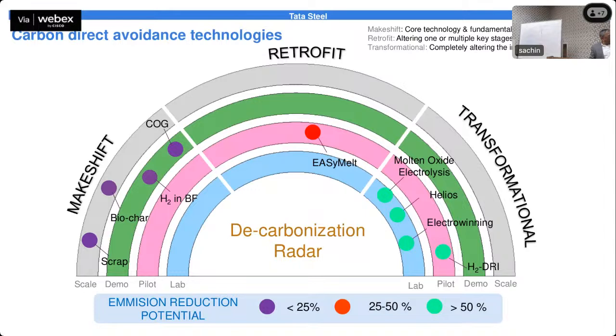But it also means, if you look at the color coding, that the emission reduction potential is only less than 25%. You cannot take care of all the carbon using these technologies. You still have the need to use carbon in the blast furnace in spite of putting this full. If you put 100% hydrogen through the tuyeres, you will still need coke in the blast furnace for other purposes.